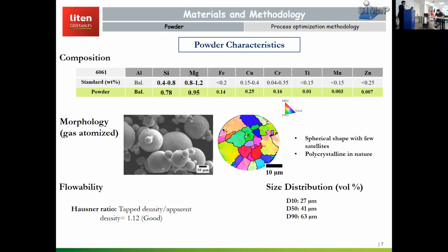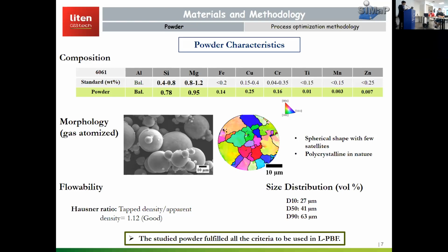In terms of flowability, because flowability of the powder is also an essential criterion in L-PBF, if your powder has good flowability, it can produce good dense parts, for example. So we quantified this flowability based on the Hausner ratio, which came out to be quite good, and that's how we concluded the powder was good in flowability. So all these criteria were fulfilled in order to be used in L-PBF.